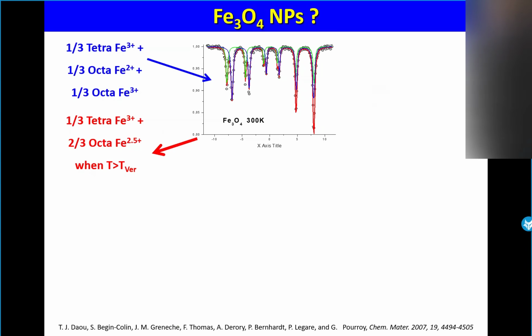So you can distinguish easily iron 2 plus and iron 3 plus. The second component is not iron 2 and not iron 3, but if you consider the values of isomer shift, it's just in between. That means above the Verwey transition, as observed by Mössbauer, you have Fe 2.5. That means it's possible to cut electrons in two parts, really to see some phenomena of delocalization.